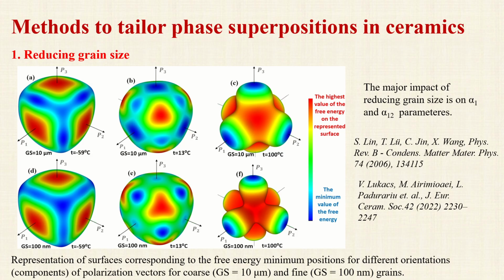For example, in these 3D diagrams, we can notice that close to room temperature, both tetragonal and orthorhombic phases present a stable minimum of energy, but a coarse ceramic is predominantly in tetragonal phase, while a fine ceramic is predominantly in orthorhombic phase. In fact, phase superpositions exist at even lower temperature values, but between orthorhombic and rhombohedral phases.